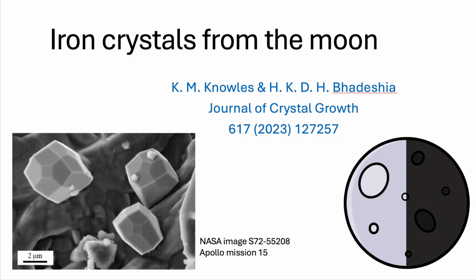Absolutely. This highly unusual geometry can really only be explained, or rationalized, as we say, by very specific local chemical conditions during that condensation process. Okay, local chemical conditions. But didn't we say the iron itself was incredibly pure? We did. And that's the key. The bulk crystal, yes, super pure iron.